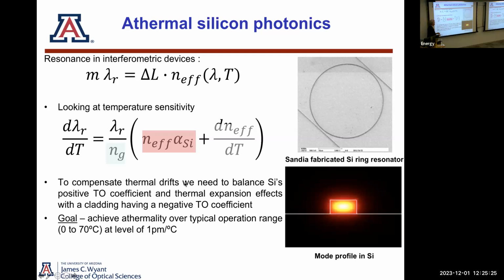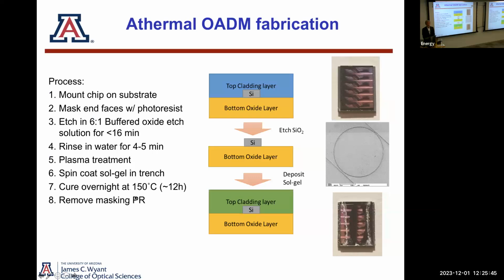Silicon actually has a pretty high temperature dependence of its optical properties, and it also would have a tendency to expand or contract. Both of those things affect this resonant wavelength. So we actually looked at trying to make it less sensitive to temperature, so you wouldn't have to control the temperature, because that's not a good thing in most cases, and it's definitely not good in a power-consuming data center. So this is the sort of work that we would do to make that possible.